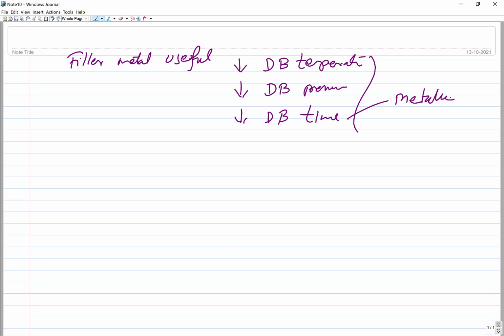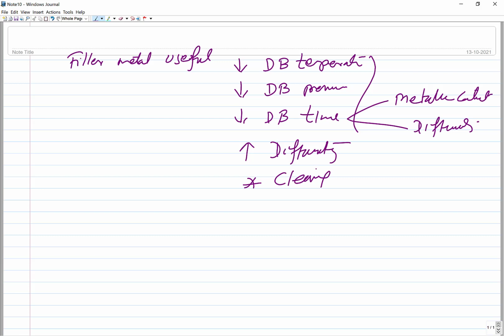And this time reduction is attributed to, one, the increased metallic contact between the components to be joined, and the second is the increased diffusivity. So it increases the diffusivity, because it acts as a diffusion accelerator, and sometimes it also helps in cleaning through the scavenging effect of the undesirable elements. So these are some of the purposes which are realized when a very suitable filler metal is selected. And these filler metals, as I said, can be in form of powders, coatings, or films and foils.